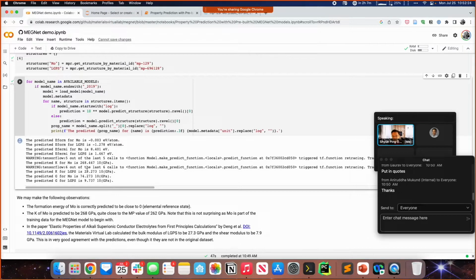This is a sulfide material, and we predict a bulk modulus of 23 gigapascal. And while this data is not in the materials project, my group actually has done elastic property calculations for alkali superionic conductors using DFT. It is in this paper over here. If you click on it, you will actually go to that paper. And our calculated bulk modulus for LGPS is about 27 gigapascal, right? And what you notice is that, again, this is very, very close to what the MEGNet models actually predict, okay?